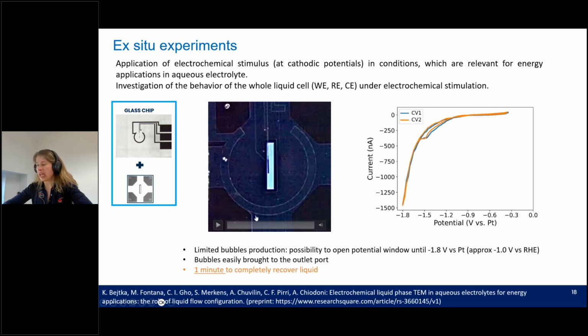The electrolyte volume is bigger and the flow is better, which means that there is increased mass transport within the channel and the bubbles can be removed more efficiently. So this is why we can open the potential window more. And we observe that the products are removed in a much more efficient way. And when the bubbles are formed, they are also brought to the outlet port very easily.